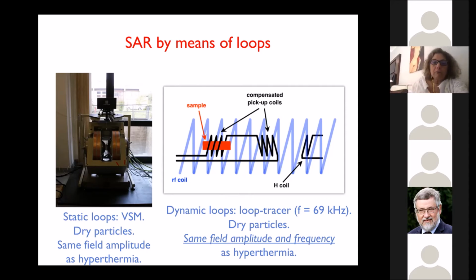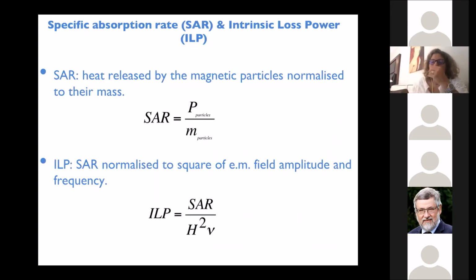We have made these measurements on dry particles, because making these measurements dispersed in liquid, as in magnetic hyperthermia, is not that easy, and the two are not comparable. These are the two important parameters in magnetic hyperthermia. Here is the heat release, the power release, which in our case is released by the magnetic particles when submitted to an AC magnetic field, and this has been calculated from the area of the hysteresis loop.